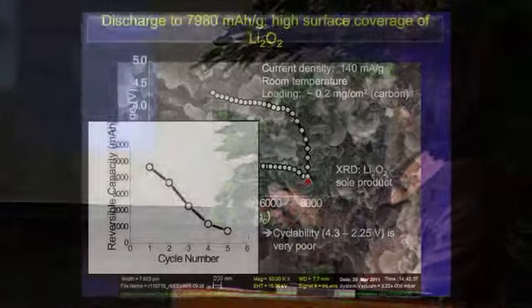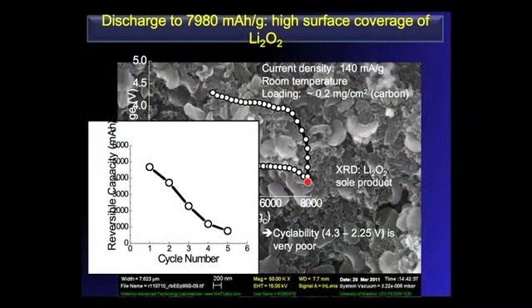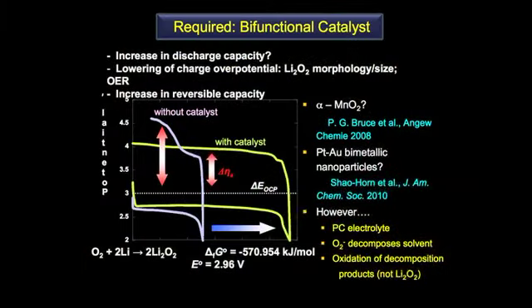At the very end of discharge, again, same thing, more toroids, no particular changes. And the problem is that carbon does not engage in oxygen evolution reactions. You have to take it to 4.5 volts. We cycle only up to 4.3 because we don't want our electrolyte to undergo decomposition. So the reversible capacity drops like a rock for a carbon type system. And so there's a real need for a bifunctional catalyst to decrease this potential on overcharge. It's not so much for this reaction, but it's for this reaction where you really need to minimize or bring down that potential in order to create reversible systems. Now, a few of these have been mentioned in the literature.